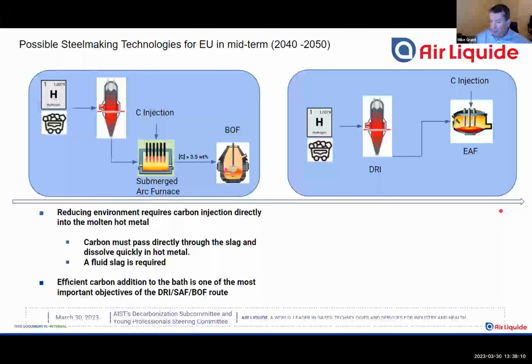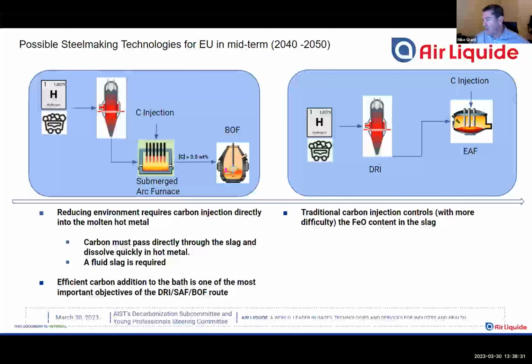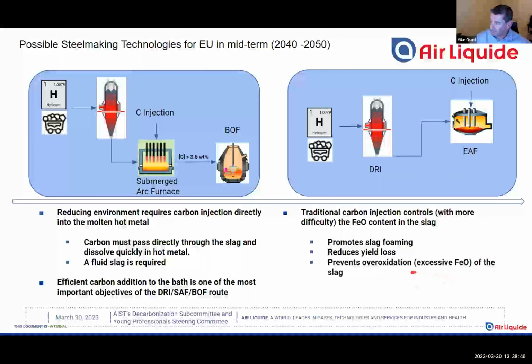If we look at the electric furnace process using the classical electric arc furnace, a traditional carbon injection is used to control the FeO content in the slag, because we're in an oxidizing environment. We're oxidizing quite a bit of our iron units. It's making FeO, which is going into the slag. We got to recuperate some of that FeO. We do that with carbon injection. And this also, if we treat the slag correctly, we get slag foaming too, which is a thermal benefit. It reduces yield loss and prevents over-oxidation. So we don't damage our refractories with excessive FeO in the slag.